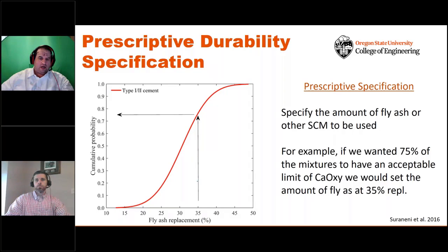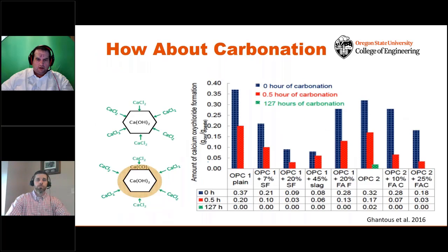And we can now start to say, well, if we don't know anything at all about our fly ash, let's pick this particular value as our specification limit. Most of the time what we've noticed is in specific regions, for example, if you wanted to do this for Ohio, you could very much limit the number of fly ashes. You don't have to consider all the ones from all across the country. Use the 13 or 15 that come into that market, and you can get a very, very tight specification that works for that local area.